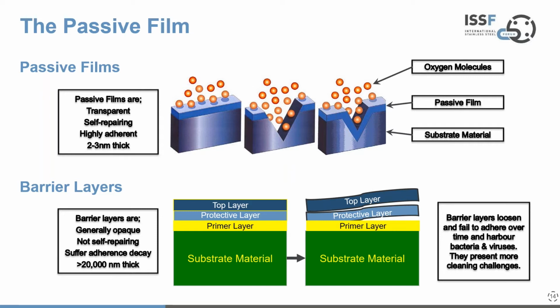The alternative is a barrier layer, some kind of coating, whether it be chemical coating or painted coatings or whatever. And these layers tend to be opaque. They're not self-repairing. They do suffer from what's known as adherence decay. They come off over time. They tend to be quite thick, 20,000 nanometers or thicker. And they are more problematic in that they loosen and fail to adhere over time. They harbor viruses and bacteria unless you choose something quite expensive. And this clearly presents more cleaning challenges. They tend to be porous to some degree, whereas the passive film is generally not porous.